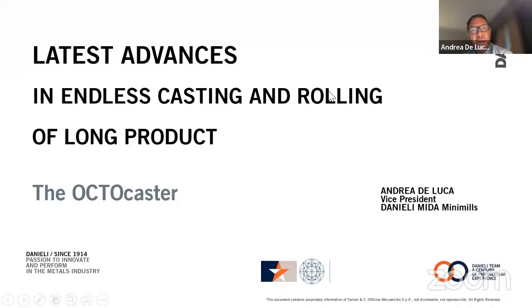what you are producing. And thanks to the endless technology, where you don't have head and tail, which means changing the size between parts of the billet, they can run very, very close to the minimum tolerance without the risk of going under tolerance. Because if you go under tolerance, you don't have primary quality and you have to scrap the product. But in this way, they can go to the very minimum and get at least 3-4% more yield. I hope to have clarified this subject.